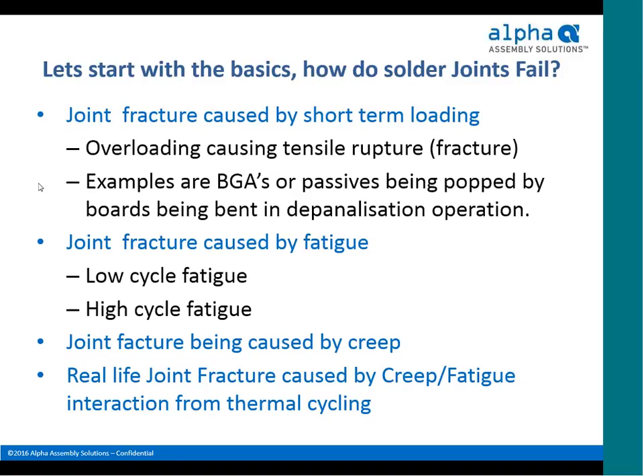However, none of these ever happen by themselves only to a solder joint. Typically, you're going to have a number of different combinations of different kinds of stresses and strains and tensile loading on solder joints at different times, for different durations, over the course of the life cycle of a solder joint. So real-life joint fracture is typically caused by a combination of creep and fatigue, and in many cases caused by the natural thermal cycling that occurs on solder assemblies.